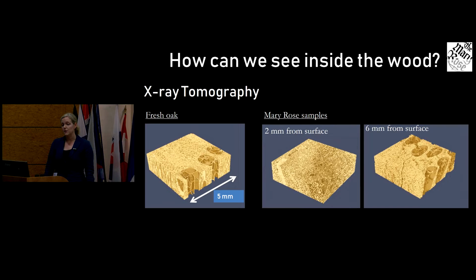against fresh oak. So in the fresh oak, you can see the wood structure, you can see the vessels, you can see the growth rings. In the Mary Rose samples near the surface, you can see that it's just a bit chaotic. That's because it's degraded. A lot of the wood structure has been compromised. But as you go down into the surface, you then start to regain some of that structure as the wood